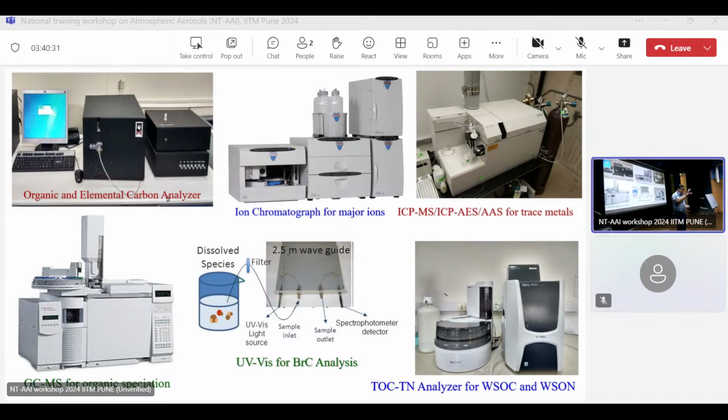Now we have the sample in solution form. When you are using flame AAS, for each element you have to put a different flame control. It is using a single wavelength. It is based on absorbance. You put some wavelength into the solution, whatever species absorb at that wavelength will absorb it, and intensity will reduce. So you know I0, I, and from that you make a calibration and calculate.